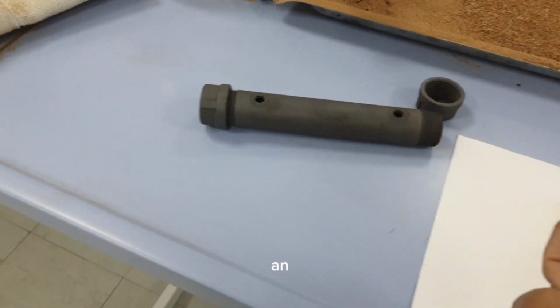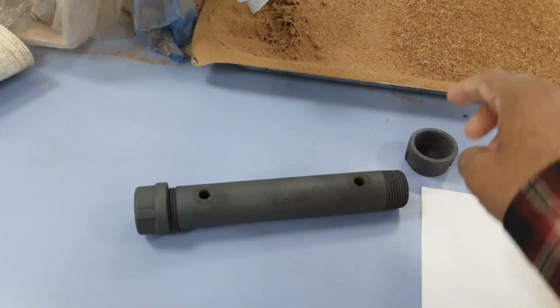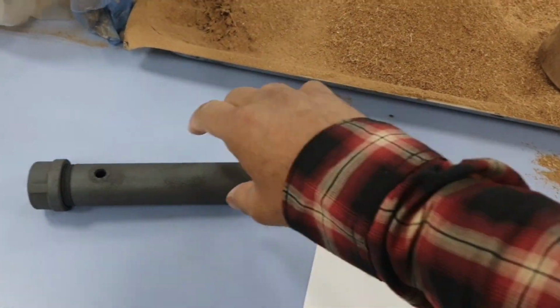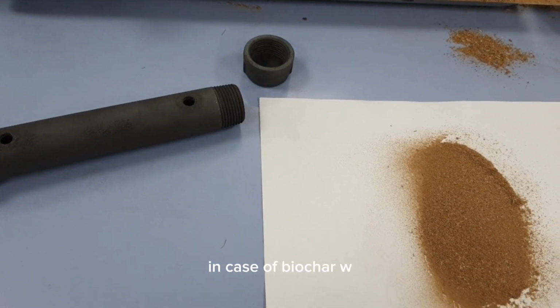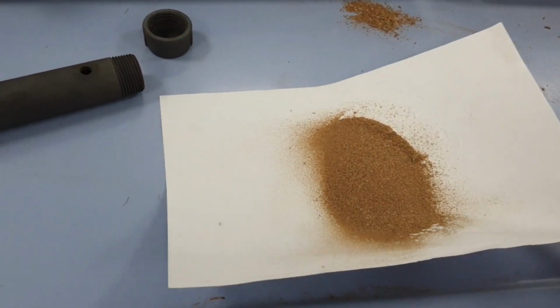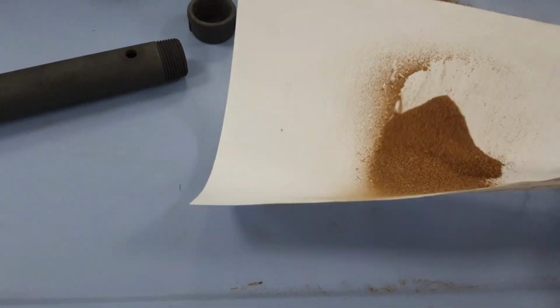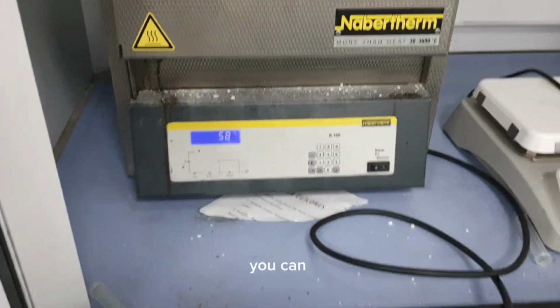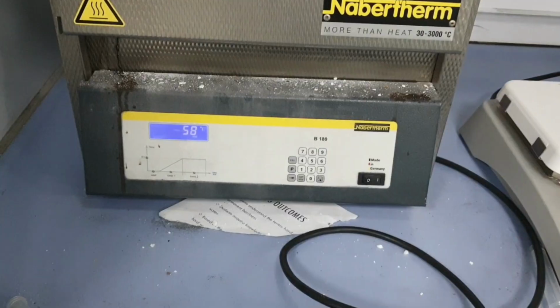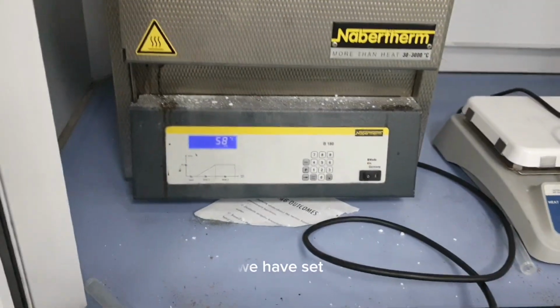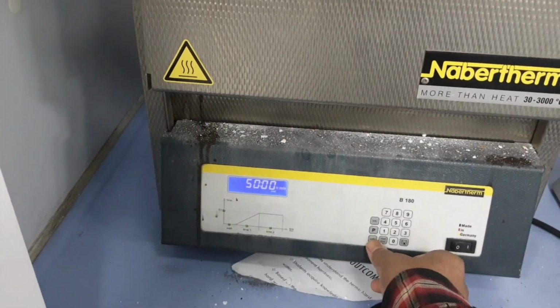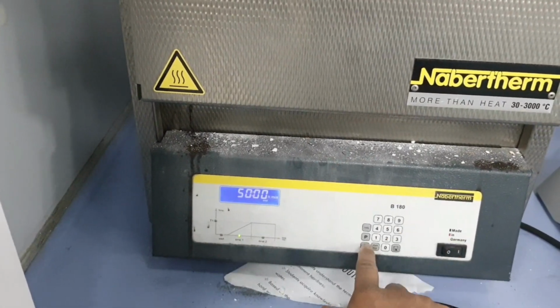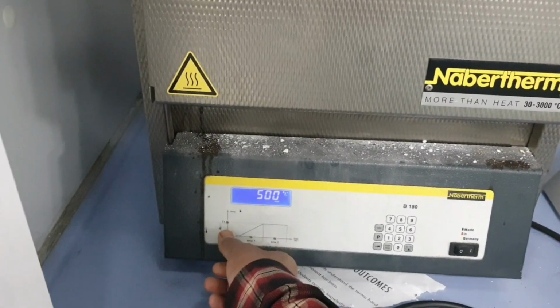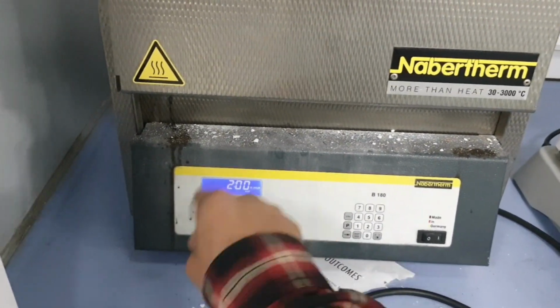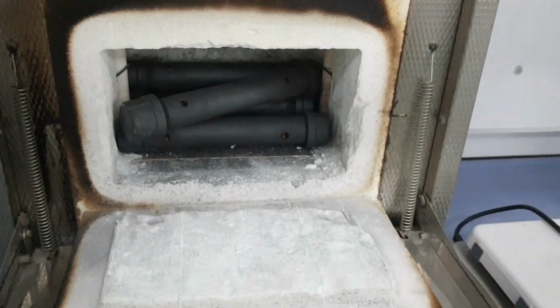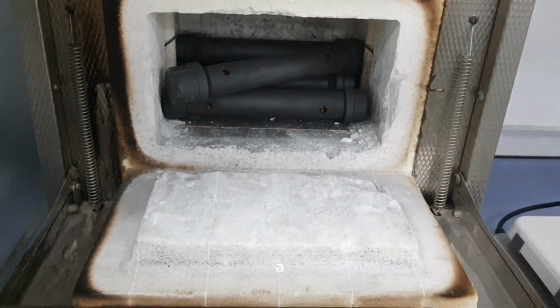We will load it here and make sure that the tubes are hand tightened and the perforation, the holes, have to be open. Because in the case of biochar, we burn the material in the presence of insufficient air. For the muffle furnace, you can see here the minimum temperature is 30 and the maximum is 3000. For this experiment, this is our holding time. In 50 minutes, it will go to 500, which is the maximum temperature it will reach. And this is our 2 hours. For 2 hours, we are going to burn the date palm material. Already we have loaded it here.